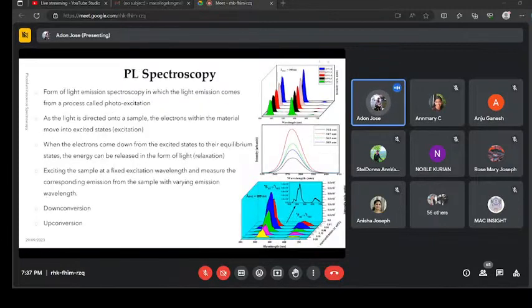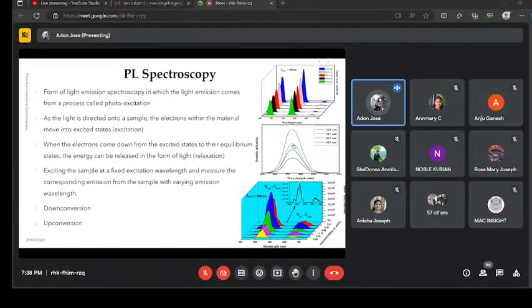Whenever we are exciting the sample with these excitation wavelengths, that means at 347, 363, and 385, this is the emission spectrum we have observed, and this is the emission intensity variation with respect to the changing excitation wavelength. In the second figure, please observe that whenever we excited the sample at 347 nanometer and recorded the emission spectra, we observed the intense emission band indicated by the red line, whereas if we record it with 363 nanometer, it is found to be less intense, and in the case of 385 nanometer, it is found to be lesser than that also.